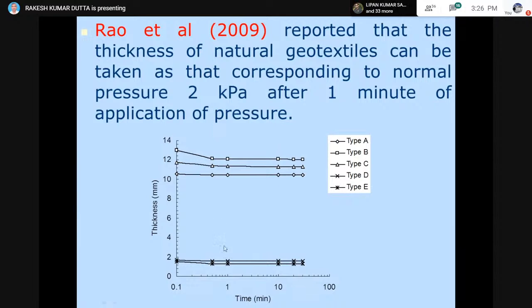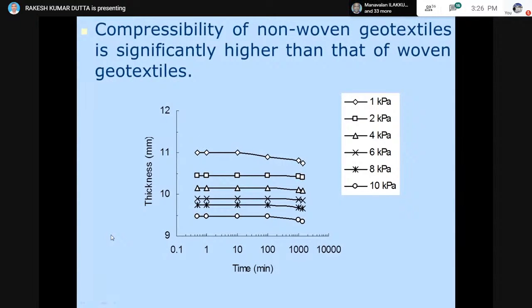The other conclusion, if you see the same picture, regards the compressibility issue. The compressibility of the non-woven geotextile as well as the woven geotextile was studied under different normal loads. The normal load was varied between 1 kPa and 10 kPa. On the x-axis we are showing the time in minutes, and the thickness is shown on the y-axis, and different curves are for different types of products. You will see that larger compression is observed in the non-woven types of geotextile in comparison to the woven geotextile.